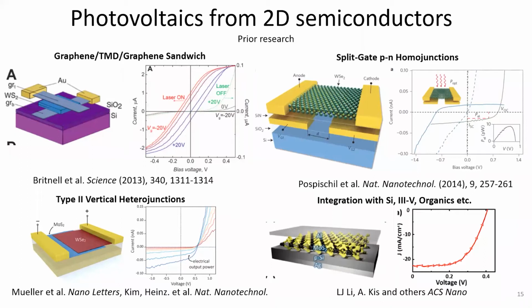And even organic semiconductors and quantum dots. But what has been unclear over here is that in most cases, it is unknown how much of the efficiency actually comes from the silicon or III-V or the organic component as opposed to MoS2. Overall, broadly speaking, I would say that most of these devices are proof of concept demonstrations. There's no useful efficiency over there. Most of them have efficiencies in the 1% or sub 1% range. And many of these devices are just proof of concept that you can see a photovoltaic effect. This includes all the way from the Schottky junctions to these sophisticated split-gated PN junctions, right?